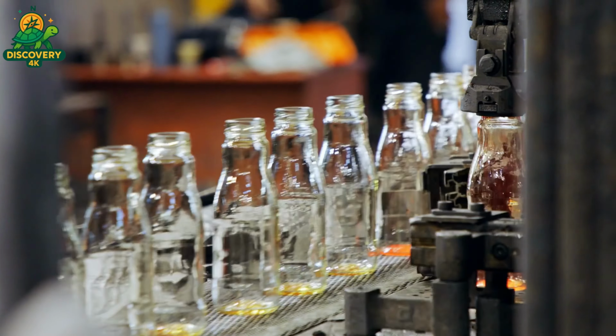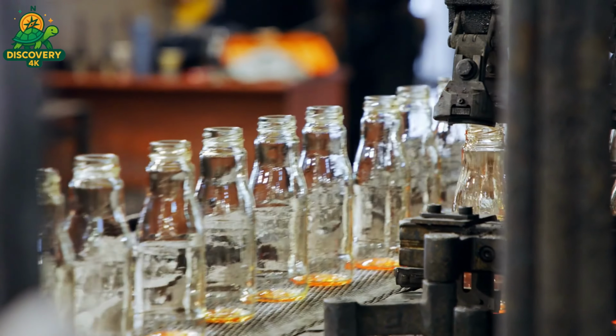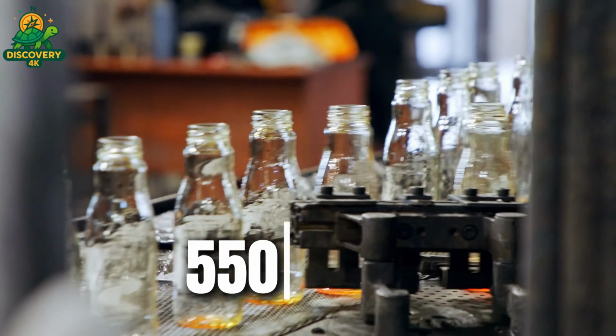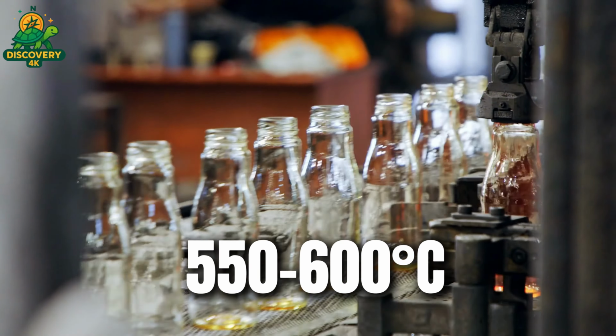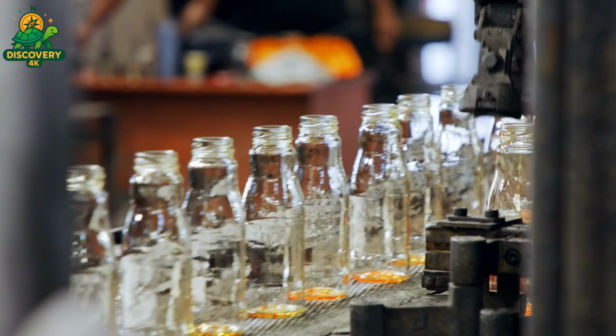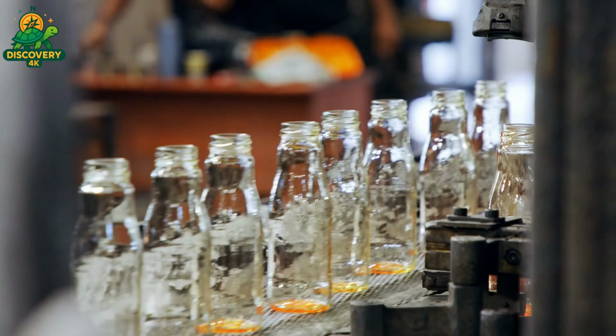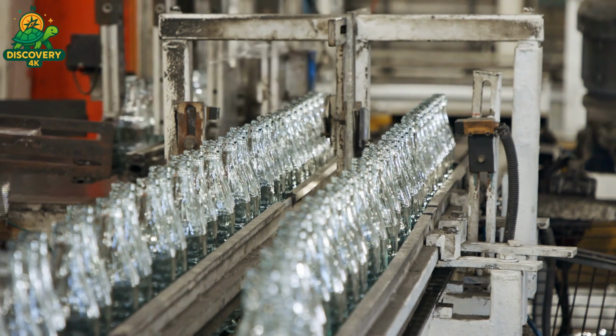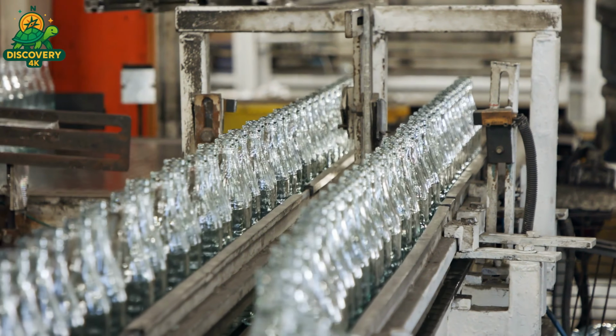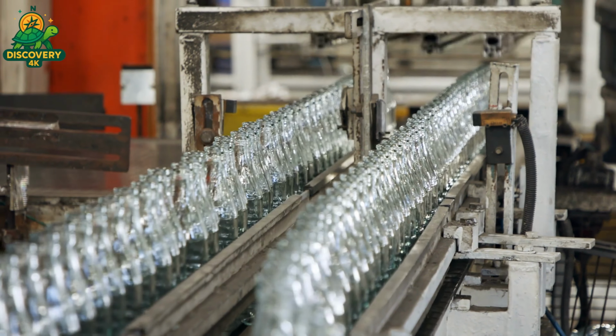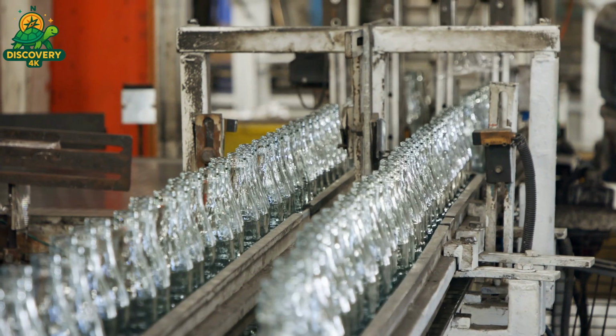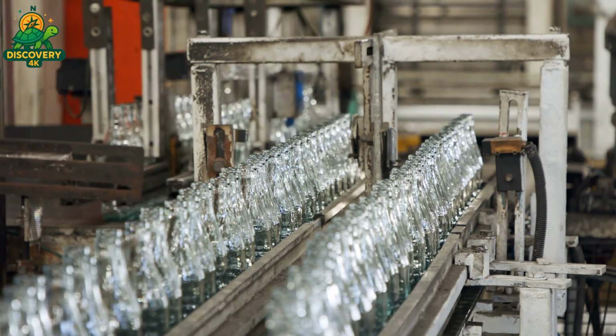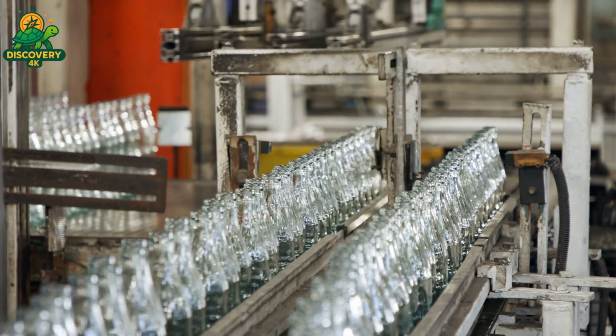Inside, temperature zones are controlled with extreme precision. Bottles enter at around 550 to 600 degrees Celsius, still glowing. Over the course of 20 to 60 minutes, the temperature drops slowly. Air jets and fans control cooling rates to prevent thermal shock. This process ensures the glass contracts evenly across all dimensions: neck, walls, and base. The result is a product that's not only strong, but also durable under pressure and thermal shifts.